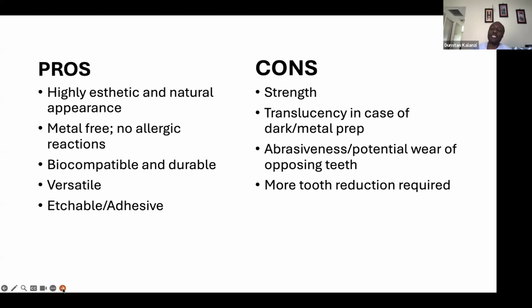However, their strength, because it's just moderate strength, can be an issue. So there are limitations. And you need to be mindful if you have a dark prep when you're using these materials, because this could be your undoing. You do a beautiful crown, but because you forgot to tell the lab to put an opaque layer in there, when you come to cement it, all that is showing through is the dark dentin, and that can throw off a patient. So these are things that you should be mindful about as you develop clinical skills.